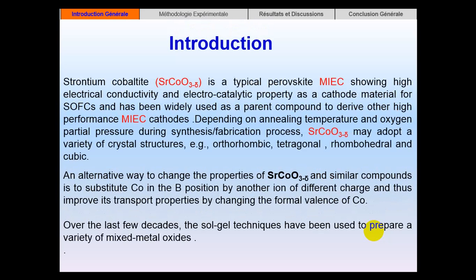Strontium cobaltite is a typical perovskite MIEC showing high electrical conductivity and electrocatalytic property as a cathode material for solid oxide fuel cells, and has been widely used as a parent compound to derive other high-performance MIEC cathodes, depending on annealing temperature and oxygen partial pressure during the synthesis fabrication process. SrCoO3-δ may adopt a variety of crystal structures, for example orthorhombic, tetragonal, rhombohedral, and cubic.